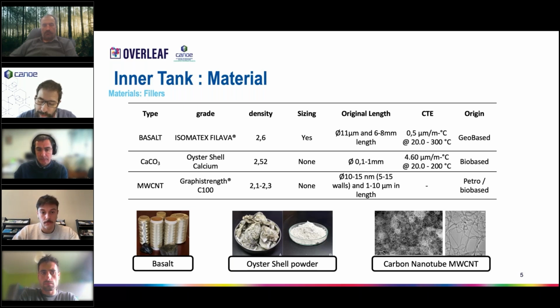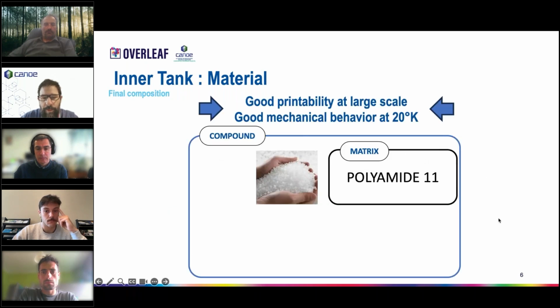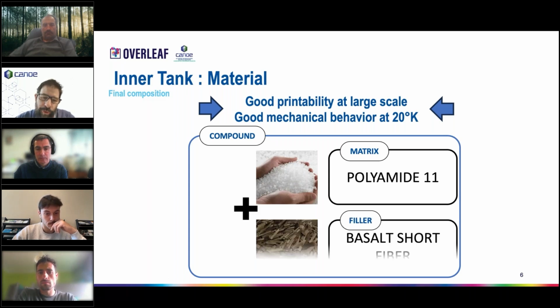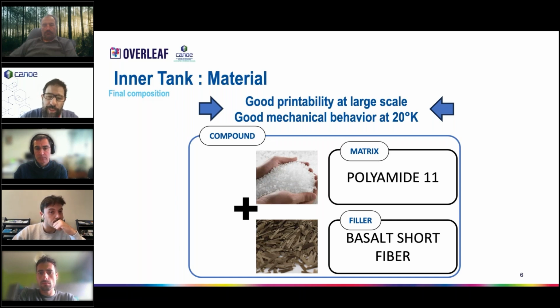So we made plenty of formulations at different ratios with different additives, etc. And finally, we focused on final formulations made of polyamide 11 for the matrix, with short basalt fibers for the reinforcement, because this combination of materials shows better printability for large-scale additive manufacturing, and shows very good mechanical behavior at 20K.